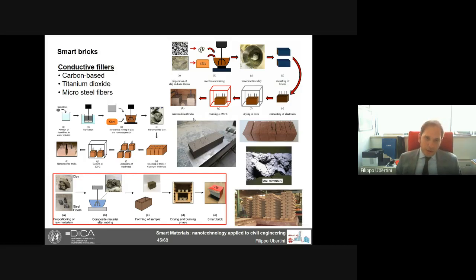Regarding the approach, in theory it is the same, but in practice it's much more difficult to have a smart brick because the brick burns. In the fabrication process it goes up to more than 1000 Celsius degrees. So for sure we could not use carbon-based inclusions unless we do very special treatments that, however, are expensive. So one possibility we proposed was to use titanium dioxide, that even if they are not really conductive particles, and by the way, they are spheroidal, so not best for percolation, still they could enhance the piezoresistivity of the material.